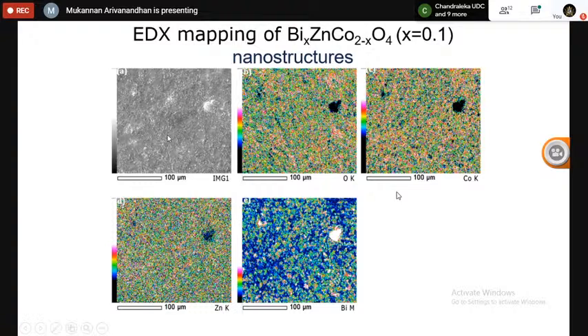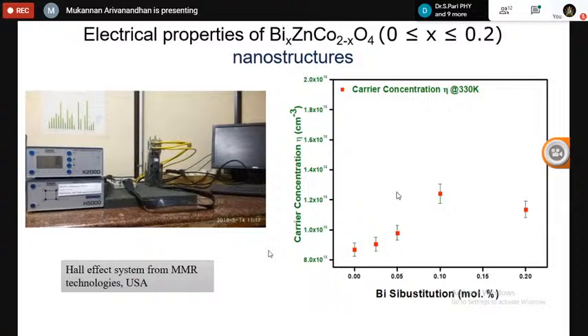So during the sintering process, the secondary phase may have precipitated on the surface, and that was recorded in the EDX mapping, which further confirms the presence of the secondary phase as observed in the X-ray diffraction analysis. And then the sample has been subjected to electrical characterization, and this is the carrier concentration, which